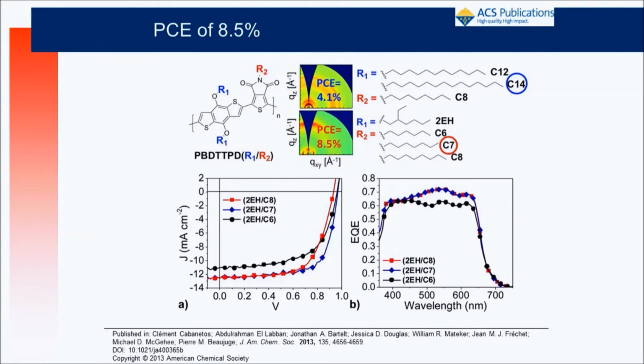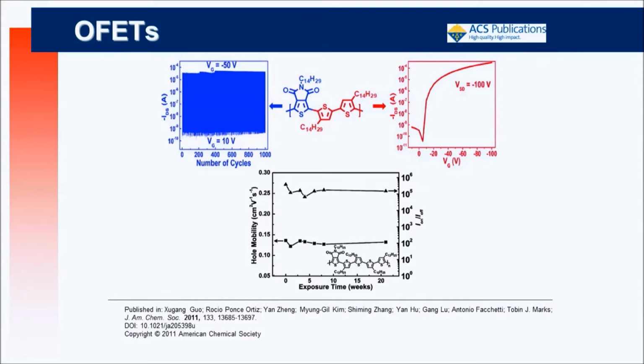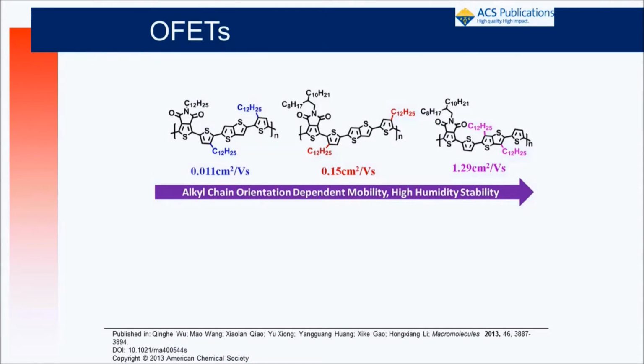Impossible to predict. So it's about 8.5 with this polymer. It's quite air stable, not so complicated. It's good also for thin film transistors, so the mobility is about 0.1 here, but it's quite air stable. And if you change the side chain and the morphology, orientation, crystallinity, and so on, you can get up to 1 in terms of mobility, which is quite good. It's comparable to amorphous silicon, for instance. So even Yuning would be pleased with this kind of polymer.